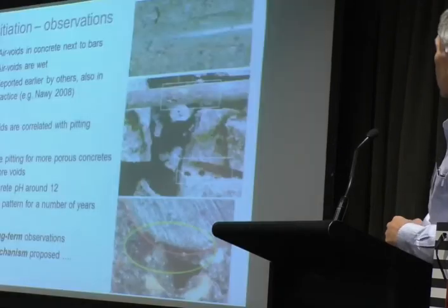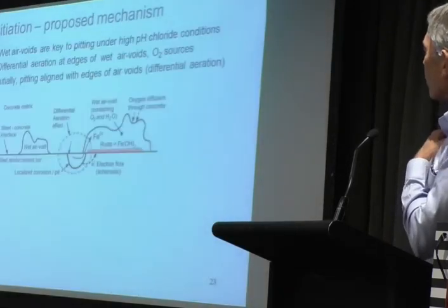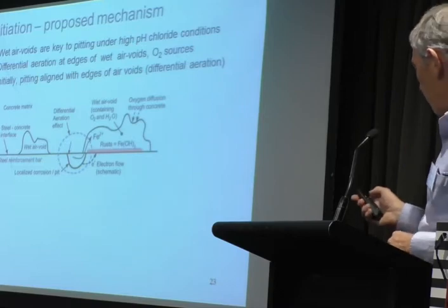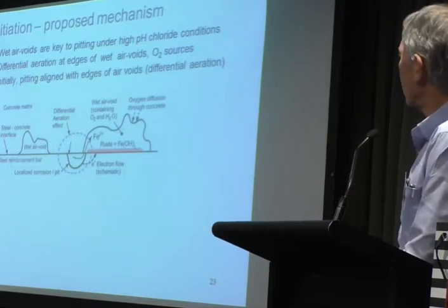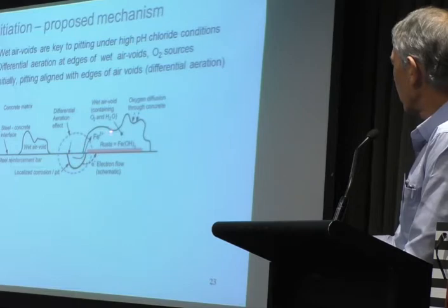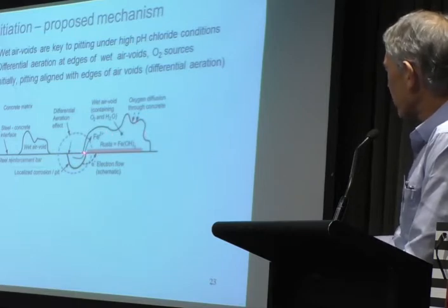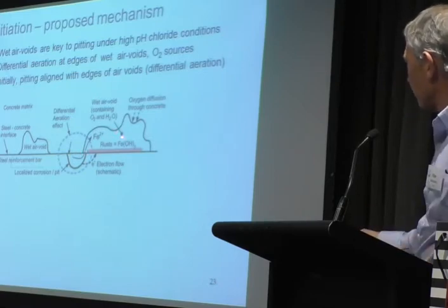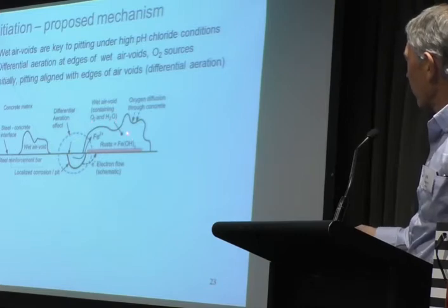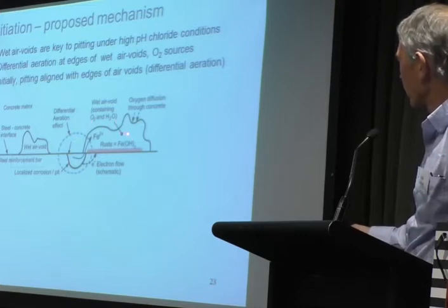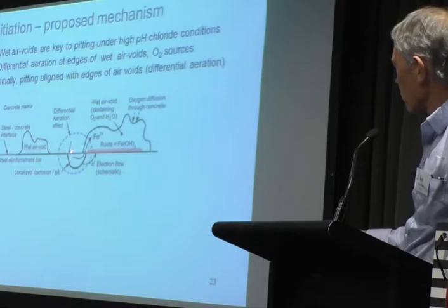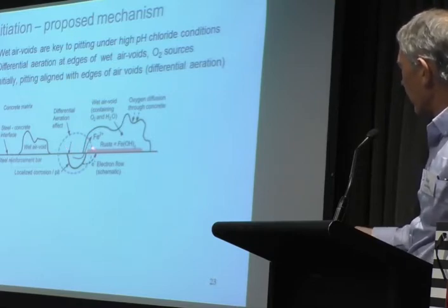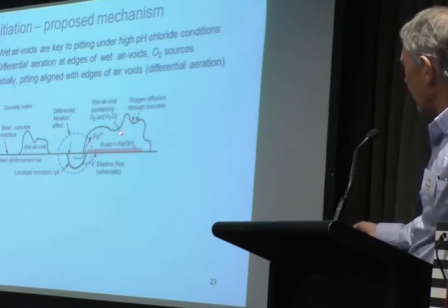Oh, I'm sorry. So what we're proposing is that something like this happens. You have an air void. This is all concrete around here. And in that region, the air void sits wetness, because all these samples are quite wet. And so oxygen and water, even if the oxygen is dissolved in the water, it's still oxygen there. And you get differential aeration to start with here, and that happens on this side as well, and eventually it corrodes into here, and all the rusts eventually end up around here somewhere.